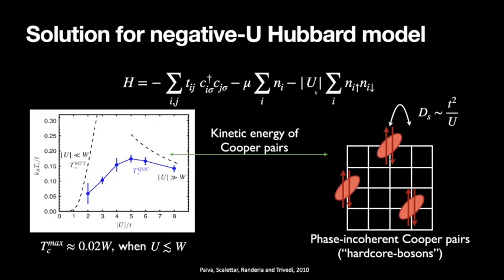Okay, and this immediately tells me that because of this explicit local interaction, my system likes to form pairs, spin singlets, which I also told you there's direct evidence for from the measurements of spin susceptibility. And then we can imagine turning on a small hopping. Okay. And so that's the picture. You have these Cooper pairs that have formed locally. There's no phase coherence.